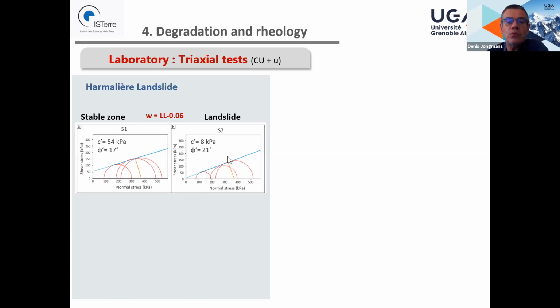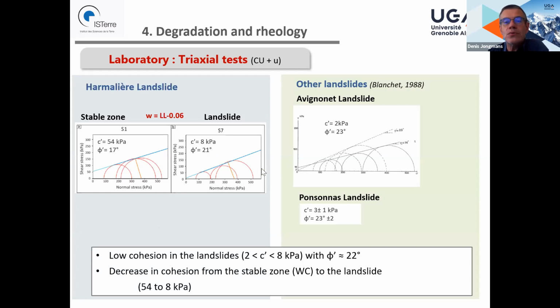And of course, it's only 2 results, so we try to have more confidence in our results by looking at what was observed in the literature on other landslides, where we are sure that the tests were made on material in the landslides. We found 2 landslides, the Avignonet landslide, which is very close to the Armalière one, and the Ponsonnas landslide. And the authors found very low cohesion values in agreement with what we found, and friction angles which are also close to the ones that we found. So we have a little more confidence in our results.